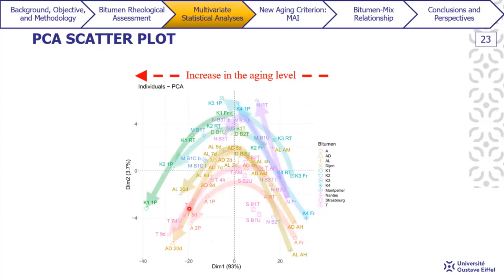And here I draw the approximate path taken by each bitumen as they age. What is interesting to note is that once each of these bitumen cross the vertical line here, we can see this inflection point that takes place here. So it seems that we have two sort of trends as our bitumen ages. PC1, which is the horizontal direction, accounts for 93%, whereas PC2, that is the vertical direction, accounts for 3.7%. The PCA scatter plot accounts for 96.7% of the overall variation.